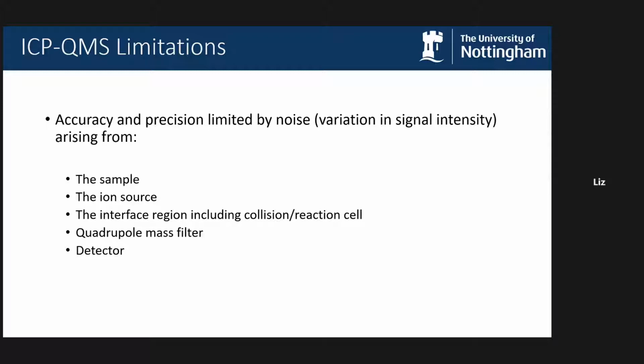Now, the detector for a quadrupole instrument is a discrete dynode detector, typically, and that necessitates a compromise between employing large analyte signal concentrations to improve counting statistics of the minor isotopes, whilst working below the point at which that detector is going to trip from pulse counting mode, which is the mode you want, into analog mode, because it can't cope with the signal that's coming at it and the number of counts it's receiving. And the other factors limiting quadrupole ICP-MS in terms of isotopic ratio measurements are spectral interferences.